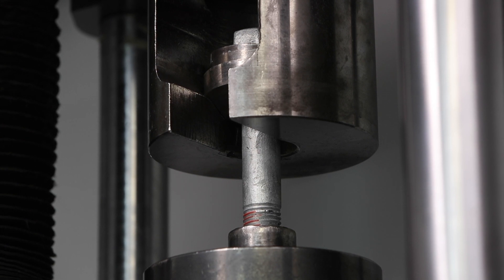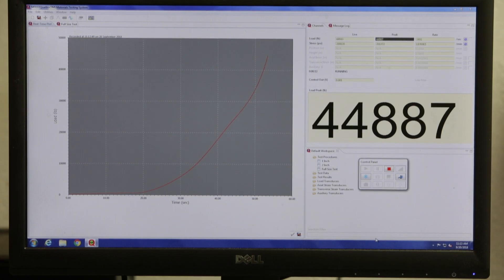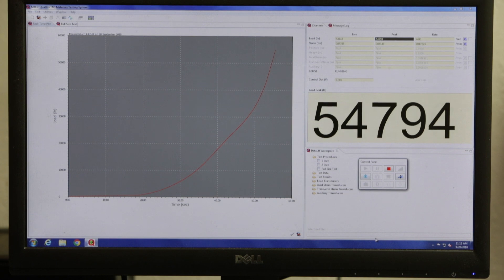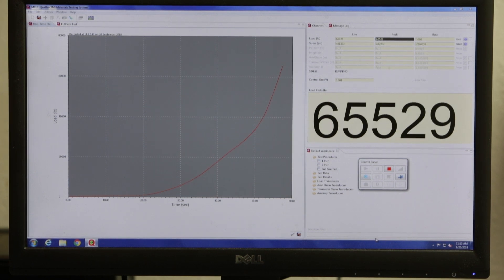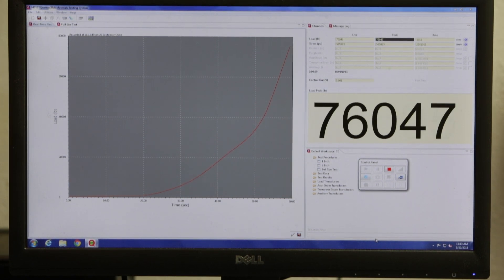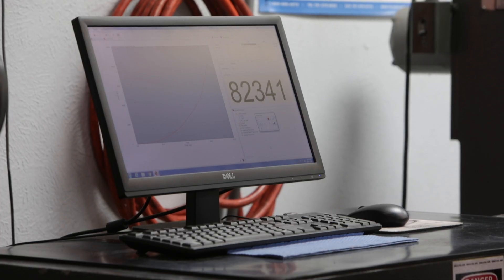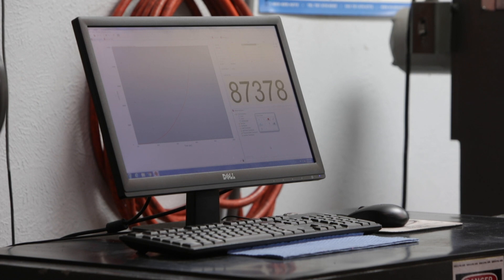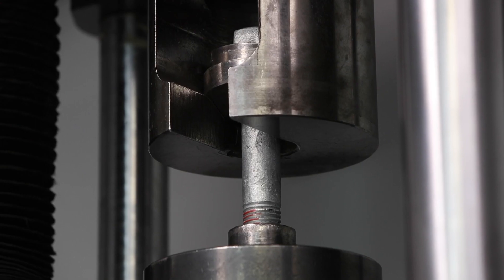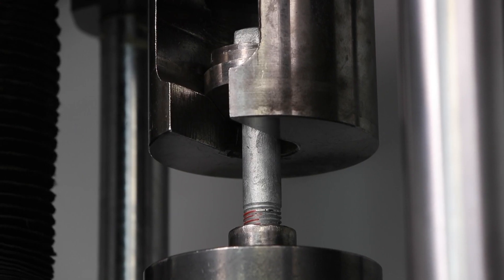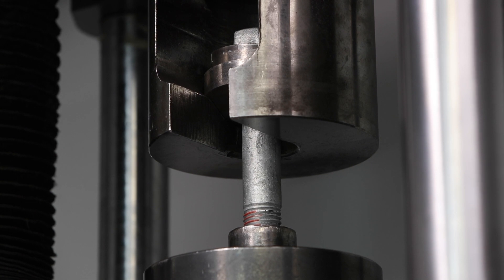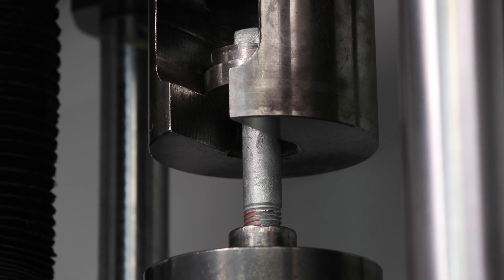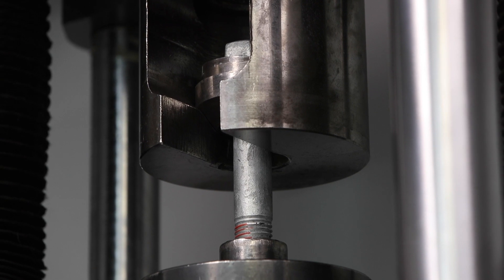Deviating from these guidelines can result in erroneously high tensile results. Generally, the higher the tensile performance of a given bolt, the fewer threads are exposed. A bolt screwed into the tooling all the way to the thread run-out of the bolt's body will result in up to 25% higher measured tensile values than if the four to six required threads are exposed.